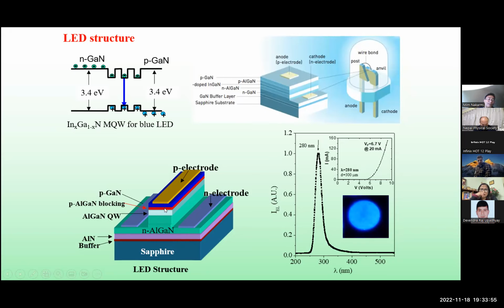So in one LED structure, it could have more than 20 different layers. And for the laser diode structure, you will have even many more. After that, these materials are etched, meaning cut down to the N-type, and contacts are put on the N-type and on the P-type. That is done after the growth is completed, and then those materials are cut into small pieces, wire bonding is put on, and after that it is encapsulated. That makes one LED, and normally one LED structure is about 300 micron by 300 micron. So if we can grow a big wafer, thousands of LEDs can be made from one wafer.